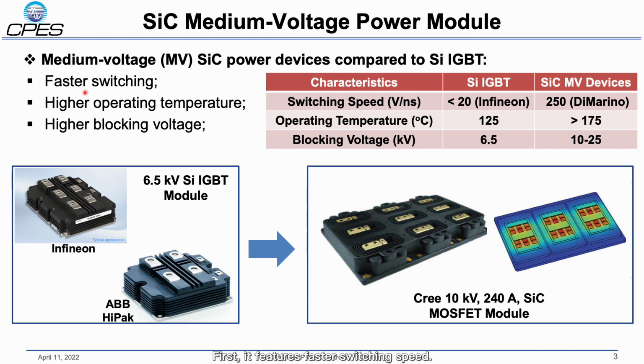First, it features faster switching speed. For the silicon IGBT module, the switching speed is limited to lower than 20 volt per nanosecond. However, silicon carbide MOSFET can switch as fast as 250 volt per nanosecond. And second one is the higher operating temperature. Because the silicon carbide has wider band gap, it can operate at higher than 175 degrees C. However, silicon IGBT can only operate below 125.